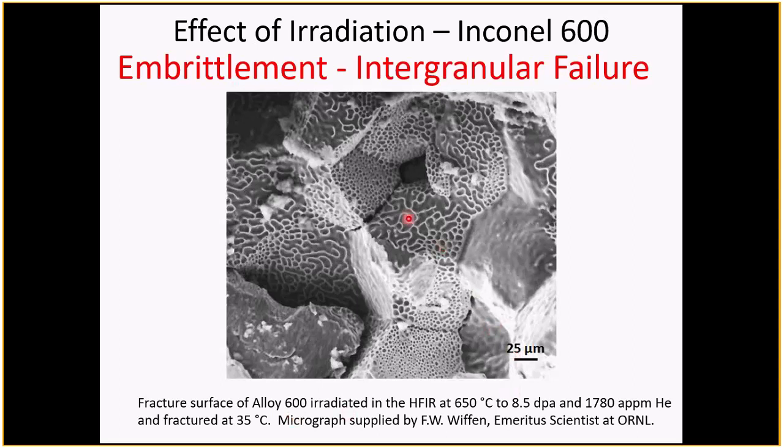And then this is the surface, and you see this funny little network. And what that is actually is we have very large cavities, and there are little ligaments of material in between the cavities, which is this white stuff here. And what you can imagine is that this is an interface in the bulk, which is very heavily decorated by very large cavities. What's interesting is that here they're all very large, here they're very small. It's like a honeycomb thing.